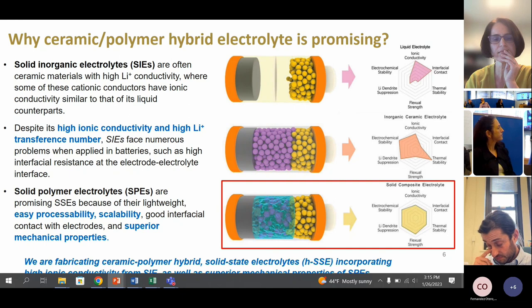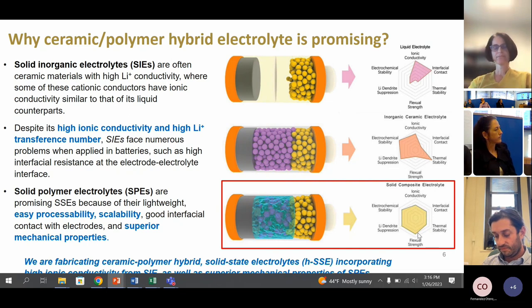So in this case, what we wanted to do is take basically a hybrid and really try to work with the best of both worlds. So these solid composites, and what we're using is a polymer and a ceramic, have much higher interfacial contact and dendrite suppression. So really the ionic conductivity and electrochemical stability are keys in the performance of this.